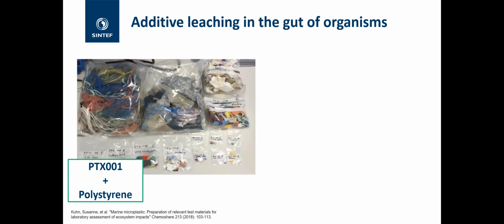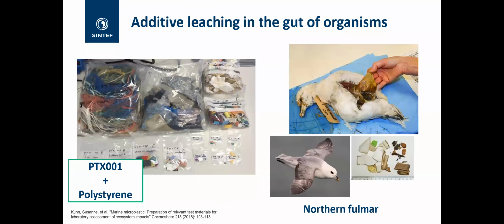Going back to this additive leaching in the gut of organisms, we did try to study this. So we took beach litter from a beach in the Netherlands, and we categorized it. We worked out what polymer type everything was. We looked at what percentage by mass, at least, it represented for the litter. And then we worked with the northern fulmar